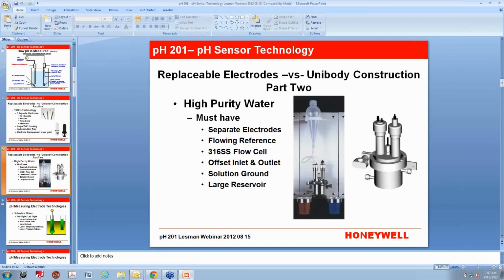You have a temperature sensor in the middle that also acts as a solution ground to take away those streaming voltage potentials which you get in high purity water, because high purity water doesn't have very many ions in it. So you have to have that solution ground. You have to have a 316 stainless steel flow cell so that you can take that to a really good earth ground. The inlet and the outlet are offset so that you don't get a siphoning action off of the outlet. If you have one of these and it's siphoning, you can usually tell because it will suck up the potassium chloride faster than it should.